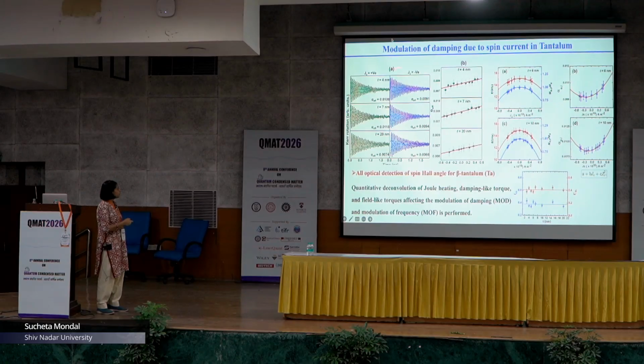Then we performed the same type of damping modulation experiment, and we found the frequency modulation is again symmetric for both sides, and then we fitted them using this formula. After fitting this asymmetric background, we actually got two different numbers for the damping-like torque efficiency. The number with the heating effect is slightly higher, around 0.6, while the number without heating is around 0.4, slightly less.